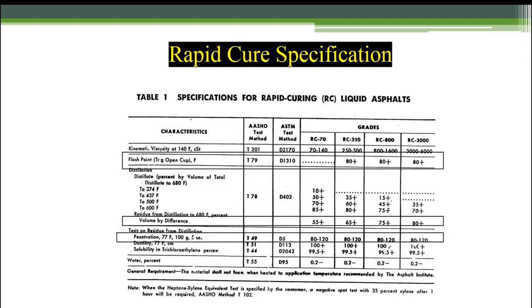But the next box, about midway down, is volume residue from distillation in percent volume by difference. As you look across there, you'll see RC70 is 55 plus, so a 55 minimum, and RC3000 is 80% minimum. Think of that: it says residue. That's the amount of asphalt that's in a gallon of that product. So in a gallon of RC70, 55% of it is actually liquid asphalt. The other 45% is gasoline. That's why the viscosity is much more liquid, or low. But as you get up to the heavier product, the RC3000, it's 80% asphalt and 20% gasoline that has to be evaporated off.